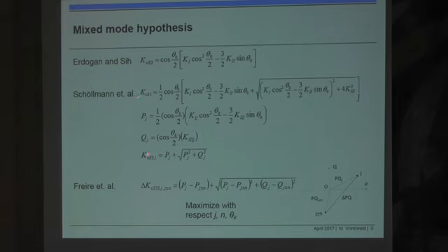And you can therefore calculate at each time step j this equivalent K of Schöllmann, and then you can make a maximizing with respect to the time steps and with respect to the angle where you are investigating, to find out some maximum value of such an equivalent K, taking all modes and time steps into account.